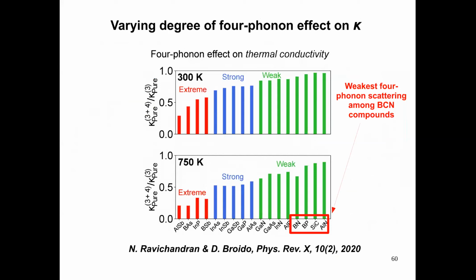If you look at the left-hand side, aluminum antimonide is a very large mass ratio compound, and does not contain boron, nitrogen, or carbon. So you would expect with these rules that the effect of 4-phonon scattering will be strong. So it will give you a good picture, but of course, if you want very quantitative results, you have to do the full calculation.